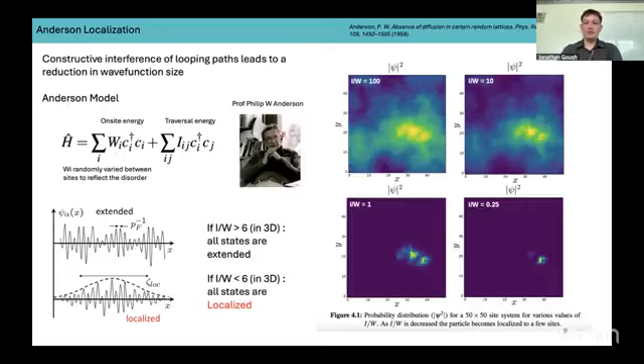So like the name suggests, it was first thought about by Professor Anderson, where he considered this very simple Hamiltonian, this two-term Hamiltonian, where you have an on-site energy, which is randomly varied to reflect the disorder. The magnitude of the disorder is given by this W term, and then some transversal energy, I. So as we increase disorder, so this top left is the weakest disorder, as we increase disorder here to here to here, you can see that the wave function shrinks. So this is basically due to these looping paths dominating your wave function.